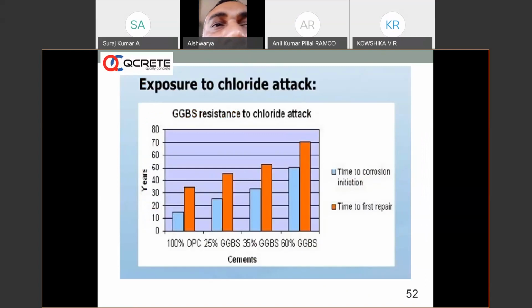Another slide shows a very important improvement of resistance to chlorides. When we are using 60% GGBS, we can see initiation of corrosion will start only after 50 years, and the time to first repair is estimated at about 70 years. Means up to 60-70 years when you are using OPC plus GGBS mixes, you don't have to bother about repairs.